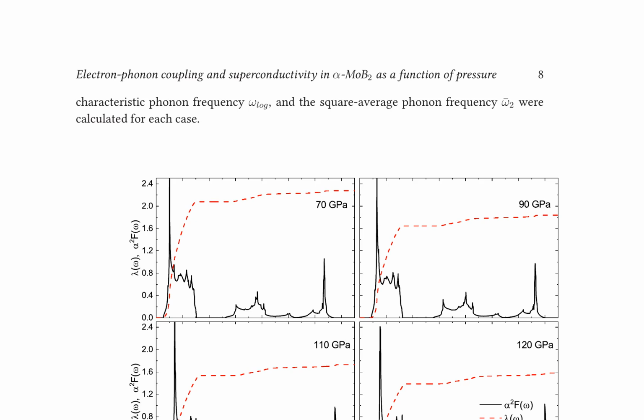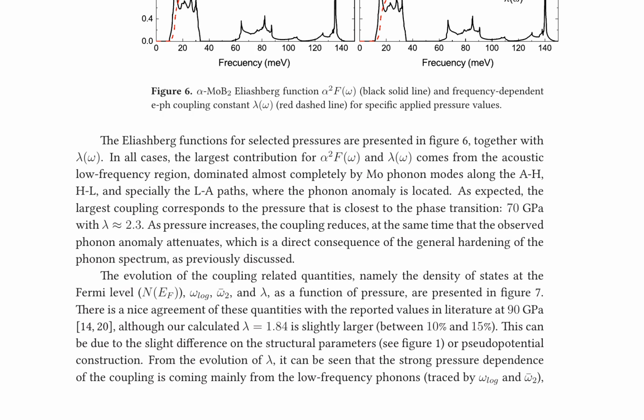The research on alpha MoB2 under varying pressure focuses on electron-phonon coupling and superconductivity. It presents the characteristic phonon frequency omega log and the square average phonon frequency omega 2 for each pressure case. The Eliashberg function alpha squared F of omega, and the frequency-dependent EPH coupling constant lambda of omega, are calculated and shown in Figure 6. The largest contribution comes from the acoustic low-frequency region, dominated by Mo phonon modes along specific paths.